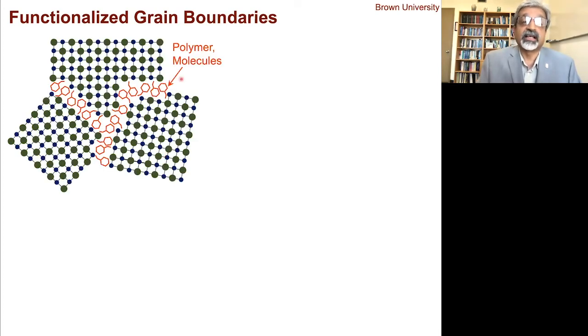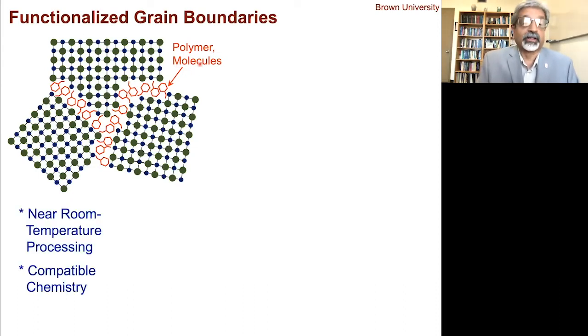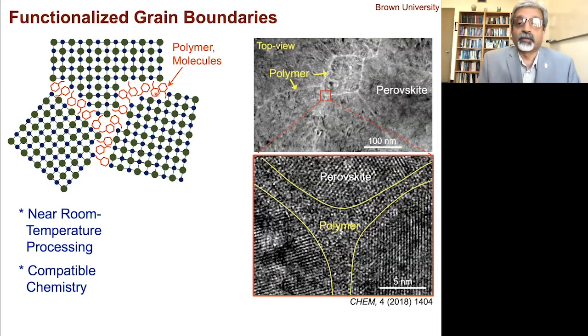Of course, these perovskites are made at a relatively low temperature and using chemistry, and therefore we can actually functionalize these grain boundaries. So the grain boundaries may not just be where the grains meet. You can actually make them smart. You can put functional moieties here like polymers, or you can put molecules. And as I said, because of the room temperature processing, you cannot really do this in, say, ceramics and metals, because the processing temperatures are so high, the polymers or molecules will simply burn. Here, we have this advantage. And a couple of examples: this shows where we put this polymer in the grain boundaries, and this polymer is hydrophobic, so it repels water and increases the stability.